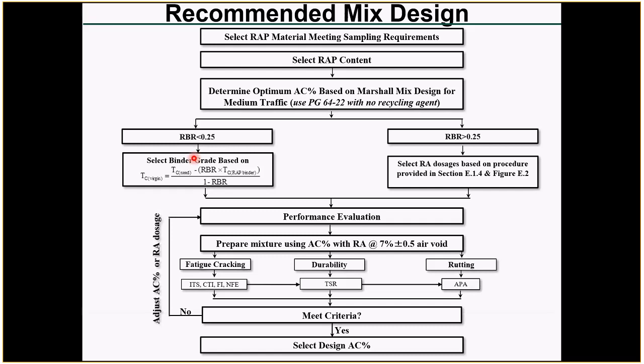Based on our results, the aromatic oil and the tall oil are the ones that we did the testing on, and basically they performed well. But again, this mix design allows you to really use any recycling agent as long as you're meeting the criteria. So we did our testing for 2 types, but this doesn't mean that those are the only types that can be used. And this is the most important: once you determine your optimum dosage, then you need to do the performance testing.